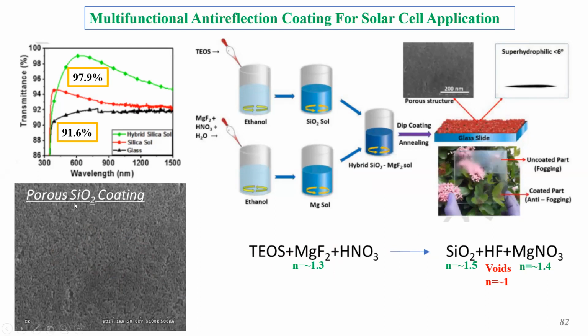So I did a lot of literature review, and the first thing I wanted to find out was why this porous structure is happening, because the TEOS synthesis procedure I used is for a normal smooth surface. How does a porous structure happen? So I made one reaction scheme, and I found that when mixing MgF2 in concentrated HNO3, I am getting HF and Mg(NO3)2. What this HF does, everybody knows, is that if we put HF on our hand, it puts a hole in our hand immediately. So it etches the silica. When I am heating the substrate at different temperatures, the HF is etching the SiO2 I am using, and this material is converting into a porous structure. And that's the reason the overall refractive index is reducing.